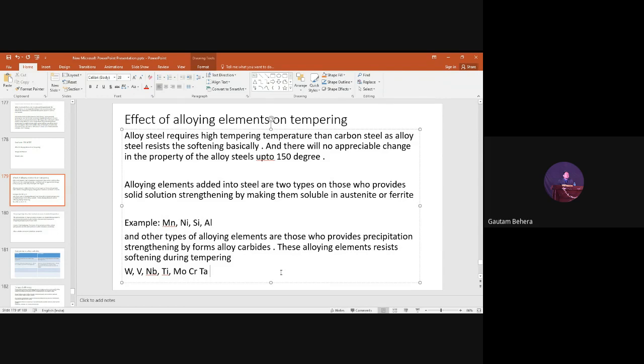There are certain alloying elements which, when added into the steels, increase the solid solution strengthening effect. Why? Because they are forming solid solution. They are soluble in the ferrite matrix or in the austenite matrix. Once they are soluble, it is a solid solution, so they provide solid solution strengthening. The best examples I can give are aluminium, manganese, silicon, nickel. If you add those alloying elements, they improve the solid solution strengthening because they are getting dissolved into the matrix, ferrite or austenite, right?